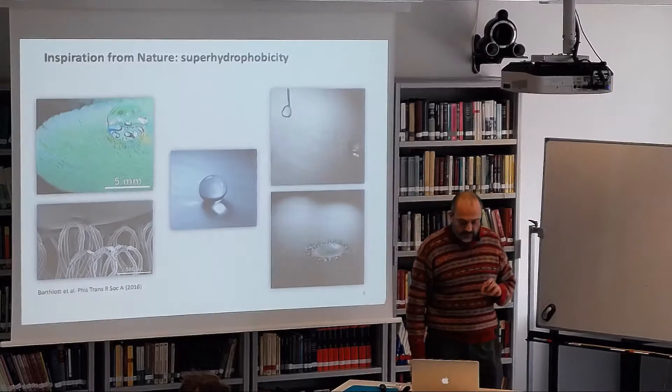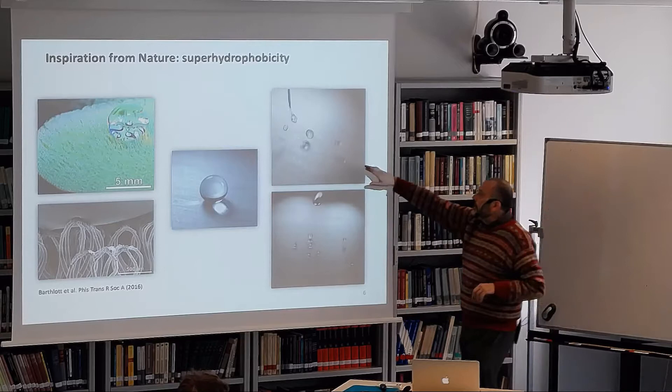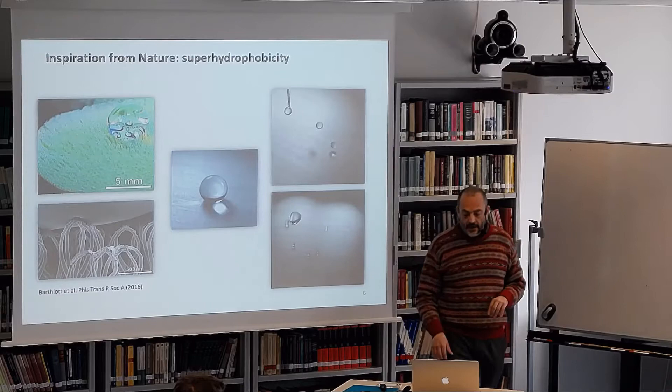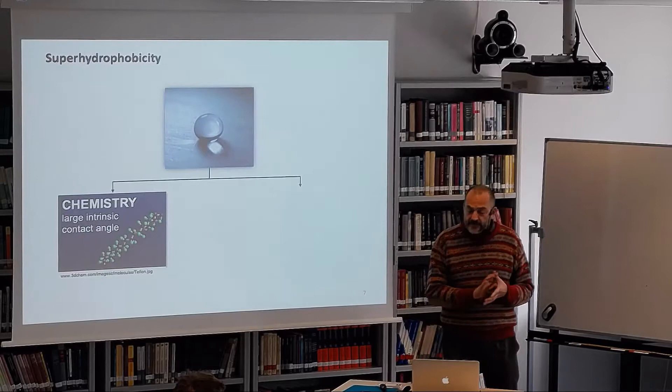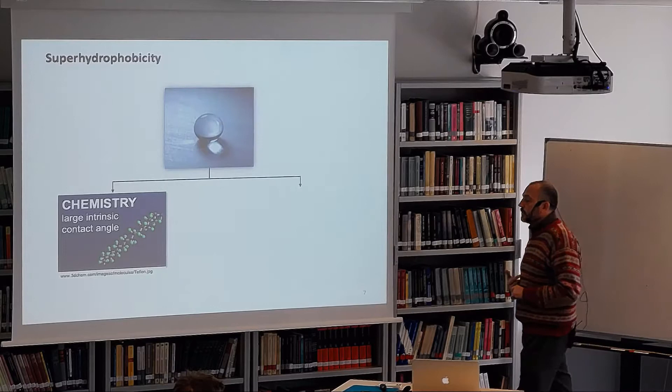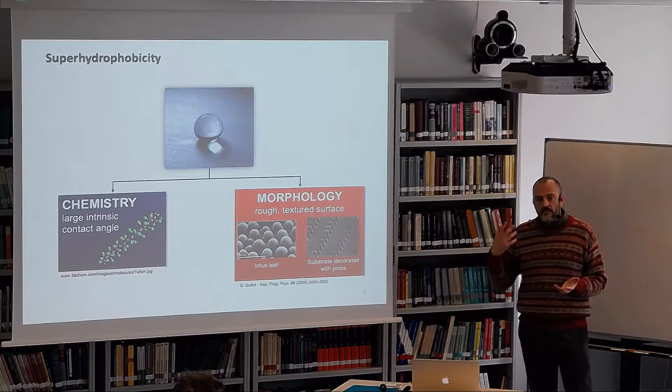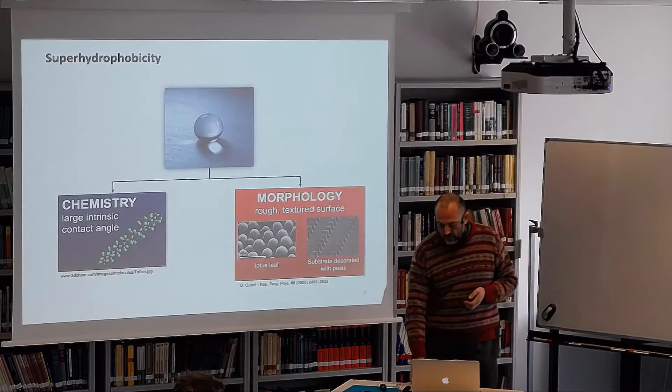Let's start with isothermal drop impact. Super-hydrophobicity is very interesting — droplets don't completely wet the surface, and if they impact, even smaller droplets roll on the surface. Super-hydrophobicity is the combination of chemistry — for example, using teflonized surfaces with a large intrinsic contact angle — and the proper morphology. The combination of chemistry and morphology gives us the chance to have a super-hydrophobic surface.